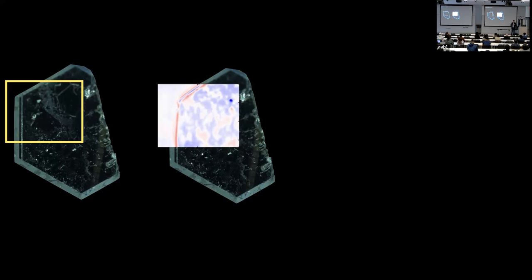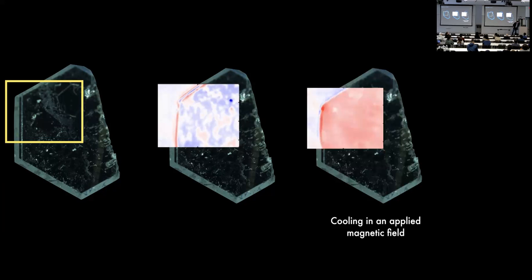A magnetic field basically can flip spins. So if you cool the system in a magnetic field, it tells it everywhere whether you should be up or whether you should be down, whether the sheep should be moving left or whether they should be moving right. And when you cool the system in a field, this is what you see. All of the domain walls have more or less gone, except maybe around a few defects. But the whole system becomes one direction of spin.